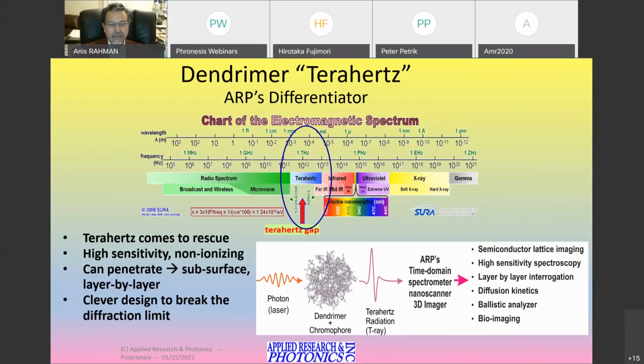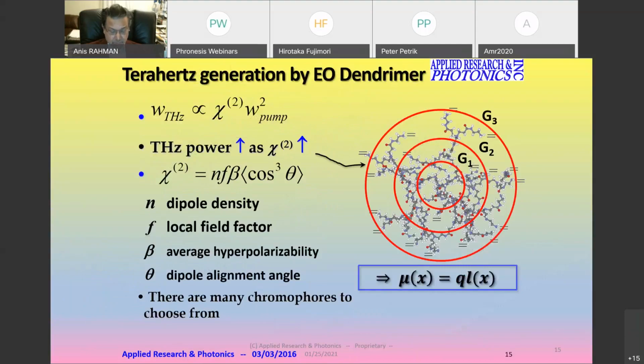So here is, in a nutshell, in the bottom cartoon, as you can see, the dendrimer is a spherical molecule. Its size depends on the generation. So we have chosen a particular generation for our work. And then we dope with chromophore to create the charge centers. And in fact, the charge center distribution is not like an inorganic lattice. They have a particular spatial distribution. And because of that distribution, when pumped with a reasonable wavelength, we get a terahertz emission from this dendrimer molecule.